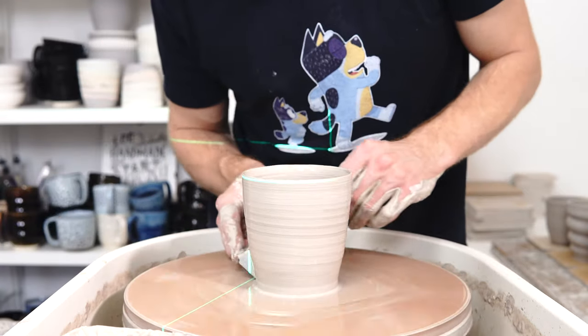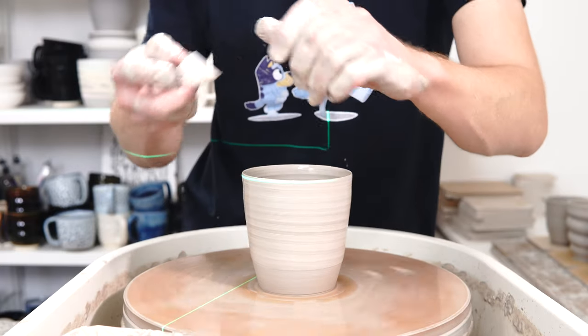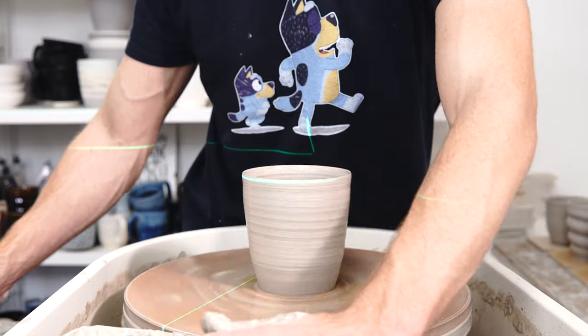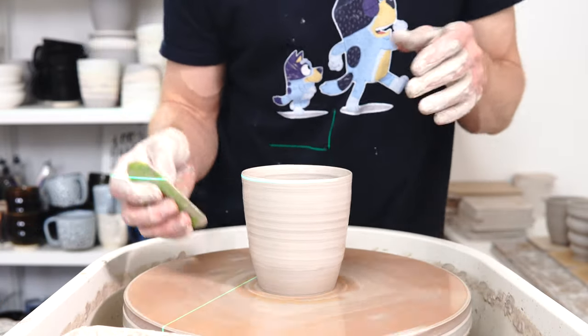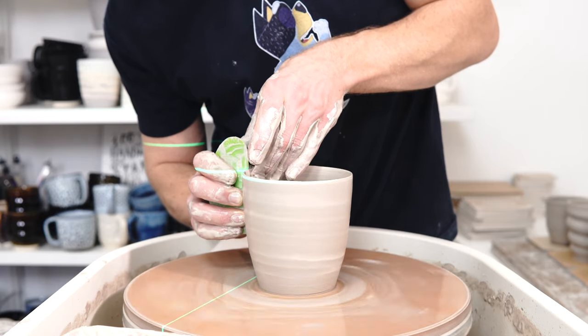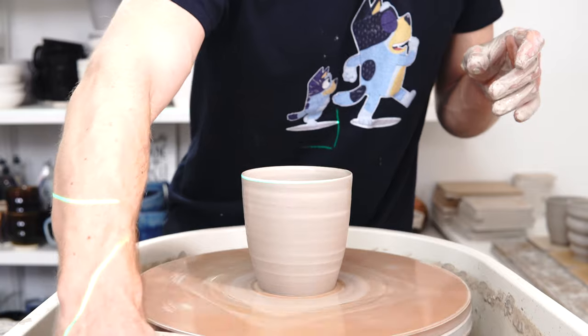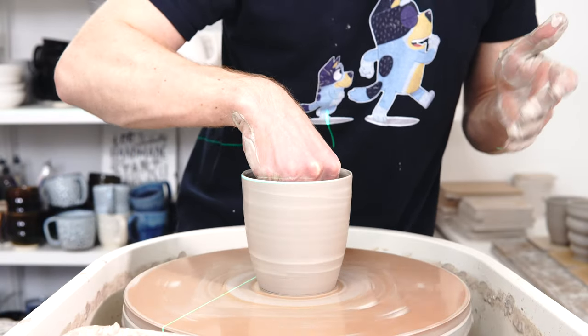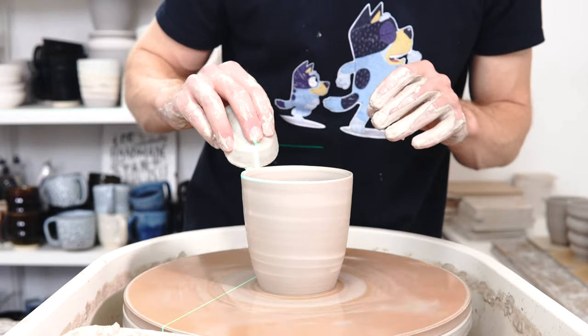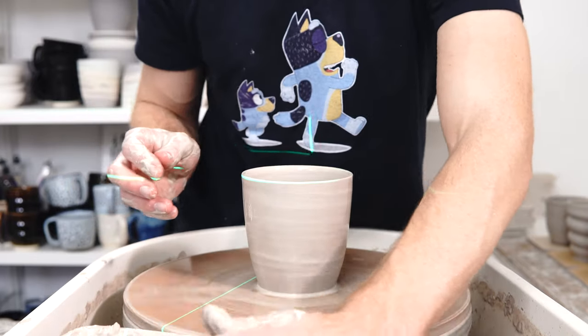Be consistent — there's consistency in how you apply your glazes, including how long you leave between coats. If you're dipping two glazes back to back, don't then leave a long gap before the second dip on another piece because it'll take up a different amount of glaze. Two things you might not immediately picture but are quite important: your bisque firing temperature, because the porosity of your bisqueware is related to the clay and bisque temperature. The hotter your bisque, the less porous the clay, meaning dip times would have to vary too.